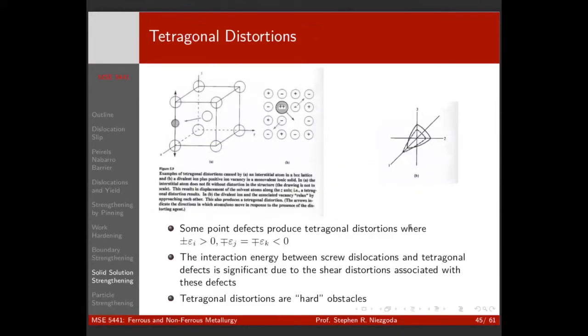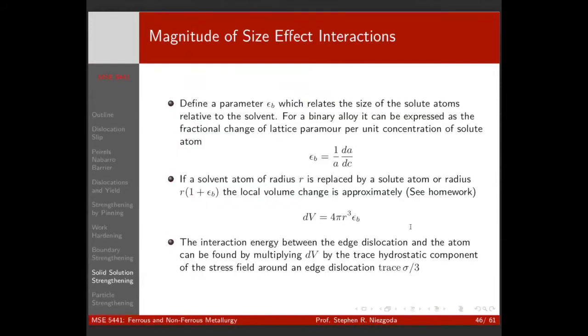Okay. So those are for what we call spherical distortions. Some point defects are what we call tetragonal distortions. And the important tetragonal distortion that we'll talk about is a carbon atom in BCC, right? That is interstitial. So interstitial in BCC gives you a stress field that isn't symmetric. And those are very hard distortions. Nitrogen in niobium. Interstitial oxygen in titanium. These are sorts of things where the size effect is much stronger because of the geometry of the crystal. And we'll talk about those more as they come up in the individual systems, right?